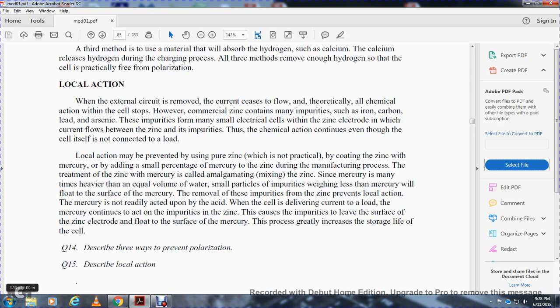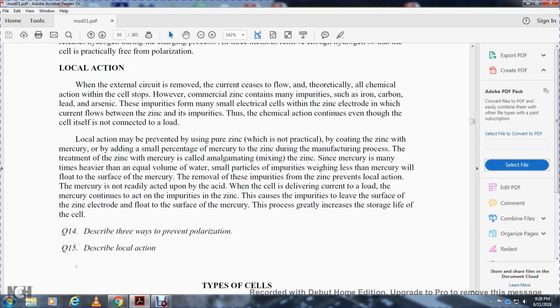Local action: when no external circuit is removing current, chemical action theoretically should stop. However, commercial zinc contains impurities such as iron, carbon, lead, and arsenic. These impurities form small electrolytic cells within the zinc electrode, and current flows between the zinc and the impurities even though the cell is not connected to a load. Local action can be prevented by using pure zinc, though this is not practical. Instead, the zinc is coated with mercury, or a small percentage of mercury is added to the zinc during manufacture — a process called amalgamation.